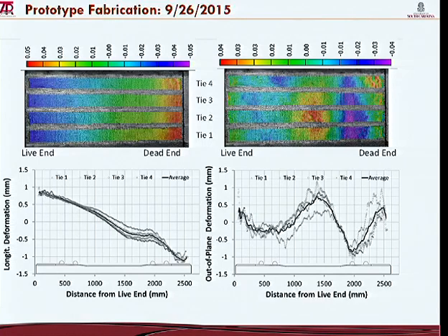The one on the left shows the longitudinal deformation. This is the live end, dead end, and for all these 4 ties, and the darker line represents the average of all, and we notice some anomaly here. One would expect a little bit of a flat area where the transfer length is, and then a straight line, and then a flat area again. But we did see some sort of an anomaly.